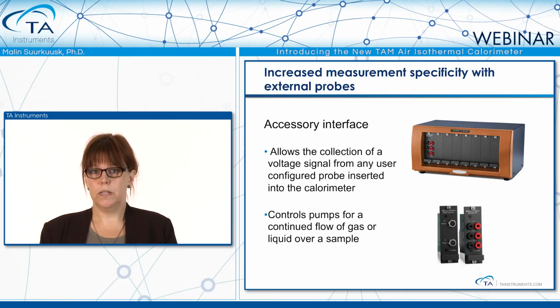What is also new with the new TAM Air is that we have the possibility to collect other signals to make the measurement more specific. You can configure your TAM Air with external probes, and the signal from this probe can be connected to the accessory interface and collected at the same time as the heat flow data. In this way, you make the non-specific heat flow data more specific if you can connect it to maybe a pH probe or oxygen probe, to see what's going on inside the calorimeter.